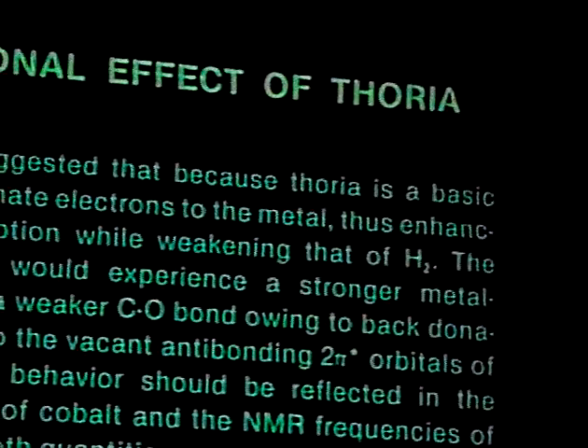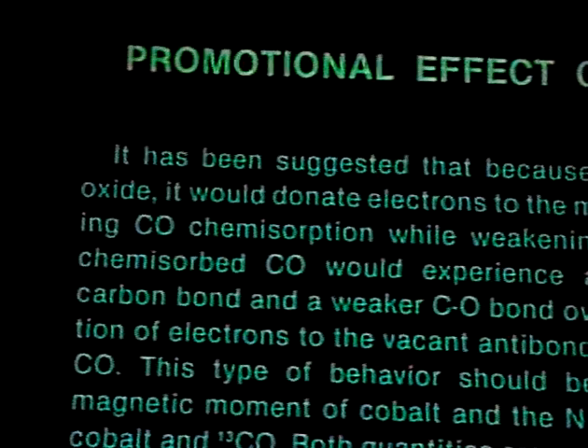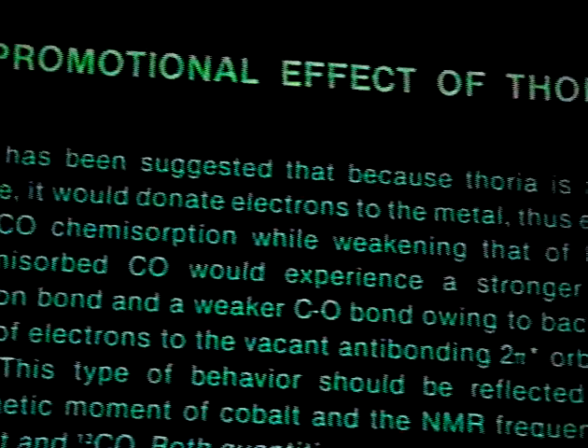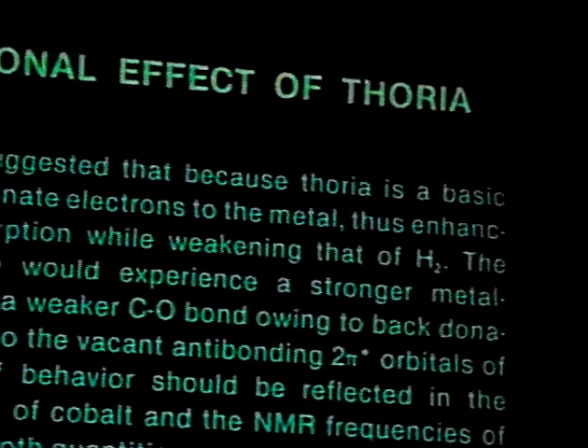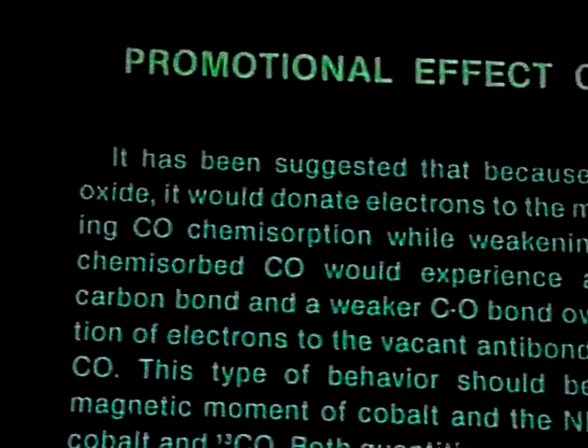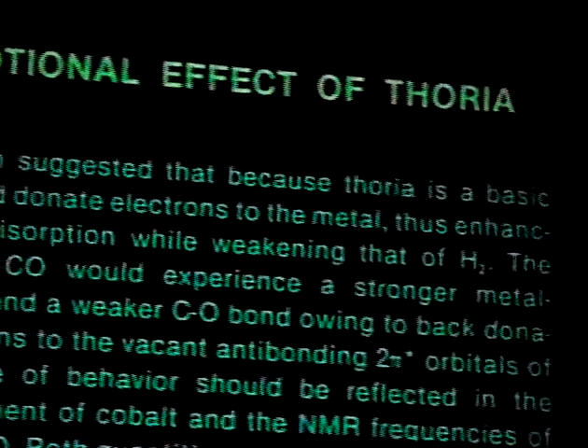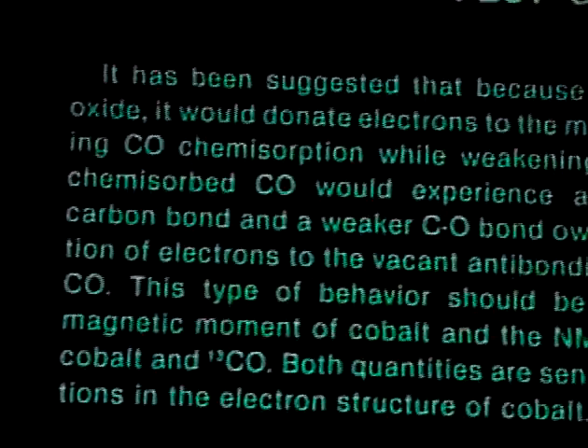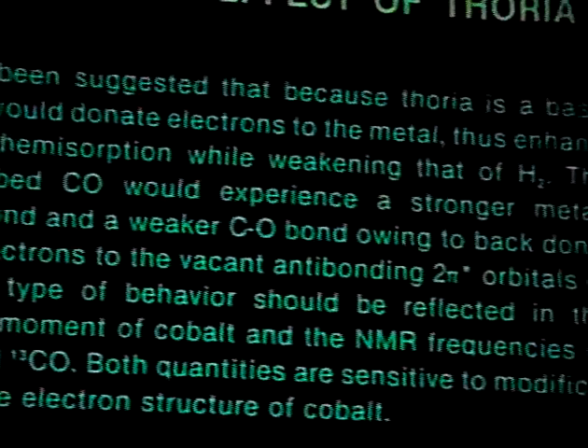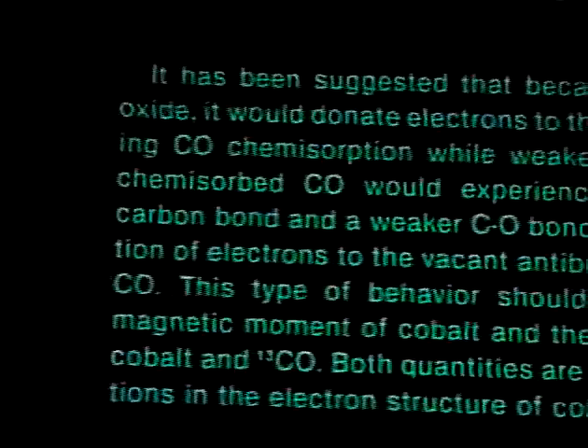Now, if this were true, it should be reflected in some of the NMR properties. For example, the surface cobalt atoms, which might pick up a fraction of an electron, say from an adsorbed CO, might show a slight shift in the resonance frequency in zero-field NMR.